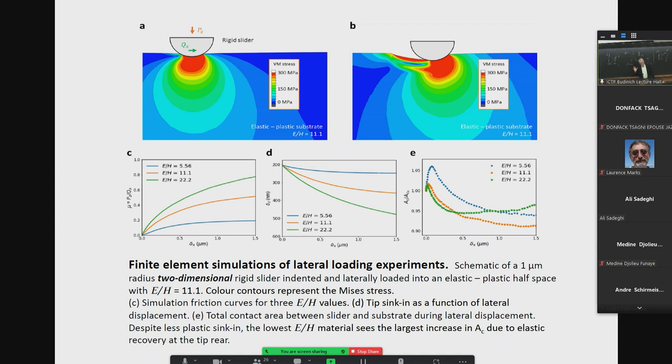But I'm not going to stress this because, in fact, there's quite a lot of things in what we're seeing experimentally which this simply cannot capture. We're going to need more information about what's happening, not least about the very thing that nanotribology is good at. When you do these things, you're making various model assumptions about what the interface shear strength is. You either use zero, or you use something, or you use some model or other, and we find it's horribly sensitive to that when you're doing a finite element analysis, and we're not in a position yet to have a definitive answer.